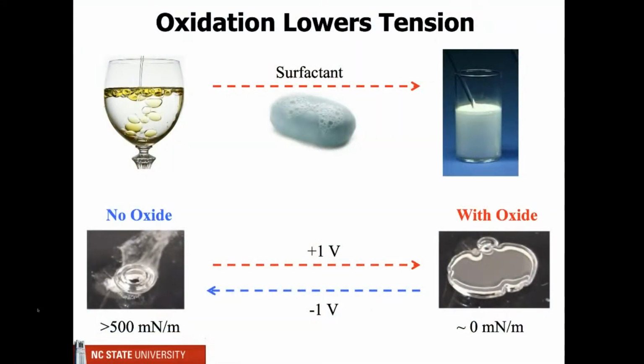And in our case, we apply 1 volt, we deposit whatever this surfactant is, and then negative 1 volt, it goes away, and the metal beads up. So completely reversible. And the neatest part is that we've gotten this to be the largest change in surface tension ever reported. And it's not even close.